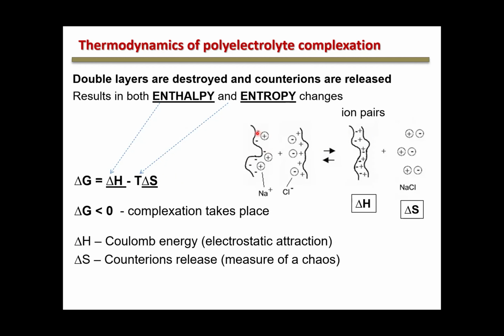So if 2 oppositely charged polymers, polyanion in this case and polycation, are interacting with each other, forming a complex, this is what's happening when you do multi-layer coating. We can consider this system from the position of double layer theory, which is basically the theory in physical chemistry that explains the redistribution of counterions from salt next to the charged solid surface. In this case, solid surface would be polyanion or polycation. And counterions are distributed around them according to double layer theory.